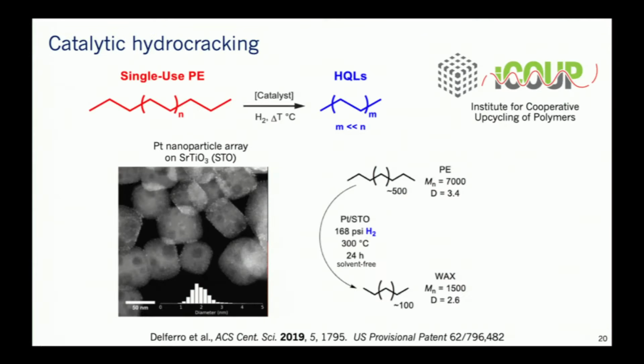Another hydrocracking example very recently from Del Ferro at Argonne National Lab involves the use of hydrogen to cleave polyethylenes over a dispersed platinum nanoparticle catalyst, and the adhesion of the polyethylene to the catalyst support, these strontium titanate nanotubes, is believed to assist in the cracking process. And the result of this is a narrow molecular weight distribution of liquid alkanes, which have obvious uses as lubricants, surfactants, and fuels if you wanted to, but this is a solvent-free, very simple process, taking polyethylene over the platinum catalyst to waxes with much lower molecular weights.